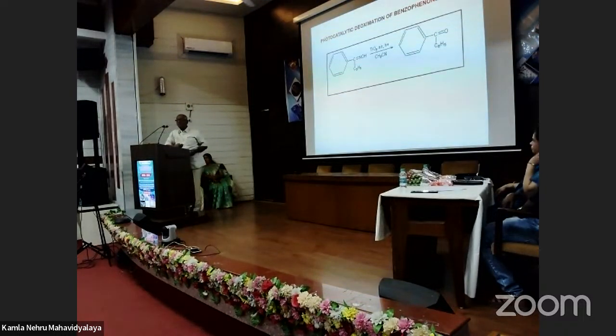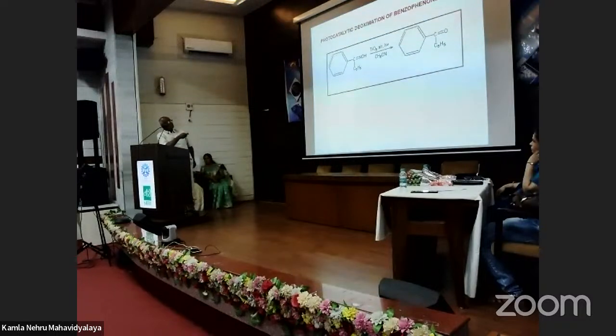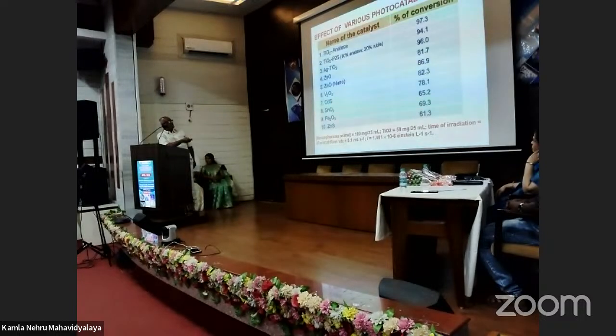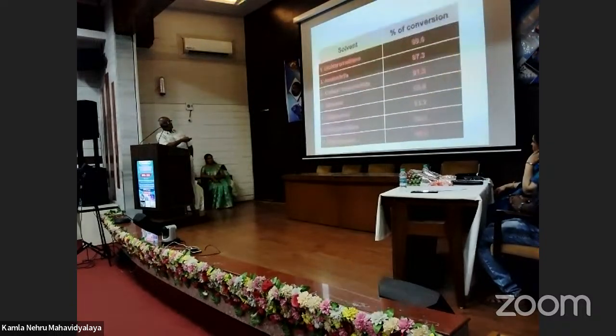And another reaction that we have performed is a deoximation, that is, the NOH is removed and then substituted by oxygen. So benzophenone oxime is taken. The deoximation reaction was done with different catalysts. The percentage of conversion is given here, the effect of the various catalysts. And you can see the silver TiO2 is very efficient when compared to the other catalysts.